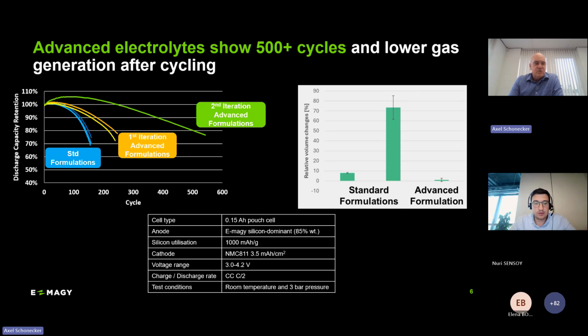If you change to advanced electrolytes, that is something that we started roughly 1.5 years ago. And the first iteration went up to 250. And today, actually, we are working with two classes of slightly different electrolytes that both have cycle lifetimes above 500 cycles. In a battery where the anode is based on 85% silicon. So it's a pure silicon anode with some conductive carbon and some binder involved in it. And these are test results against NMC 811 in 3.5 milliampere hours per square centimeter cell. So actually already cells that are close to industrial applications. Also, these advanced electrolytes, they have advantages in gas formation, so they are very benign, and they can be applied in batteries.